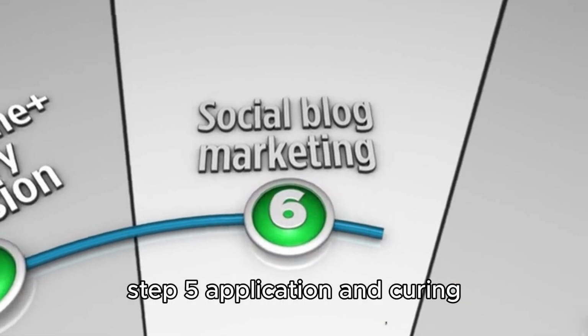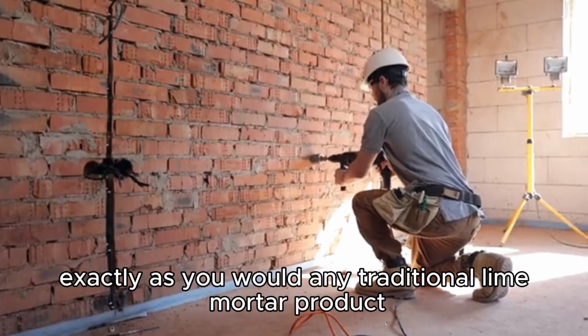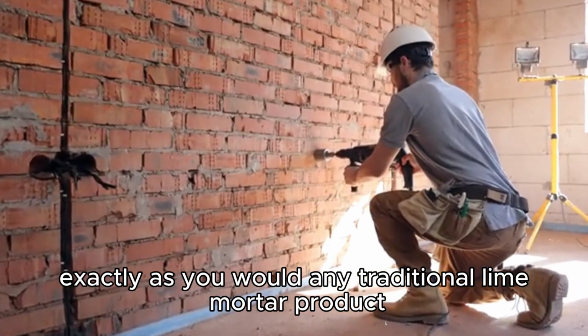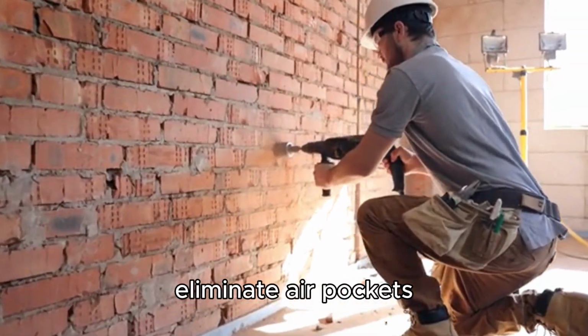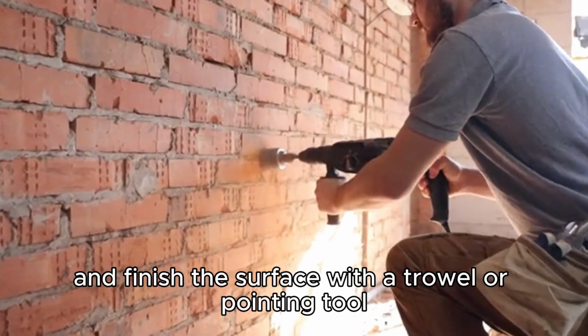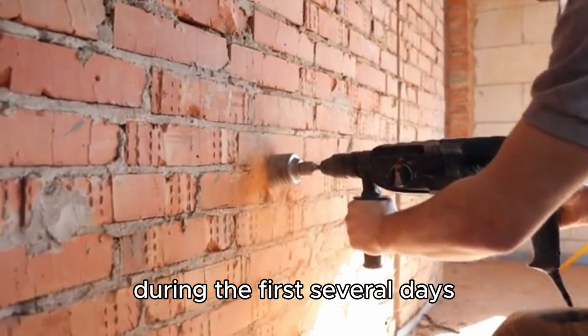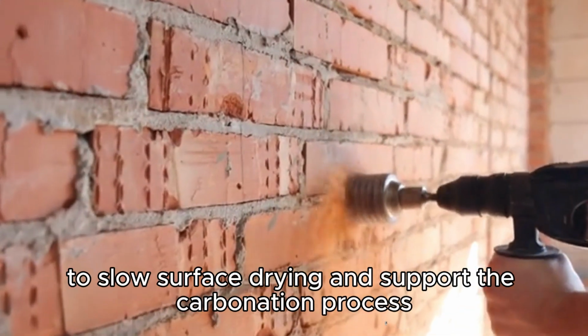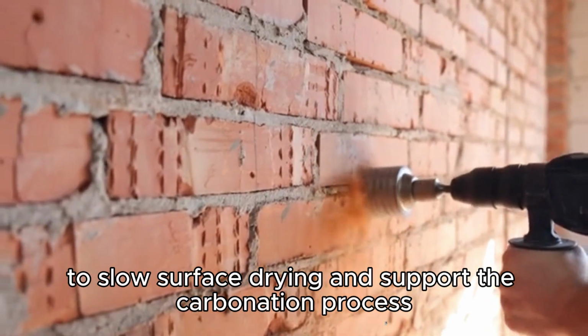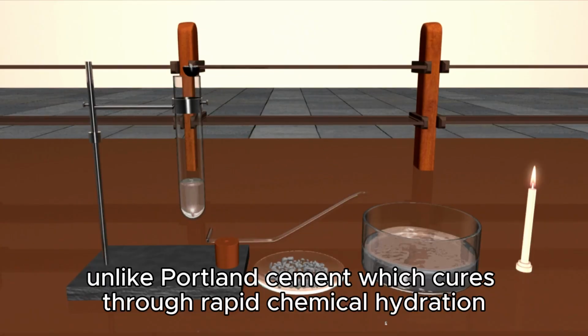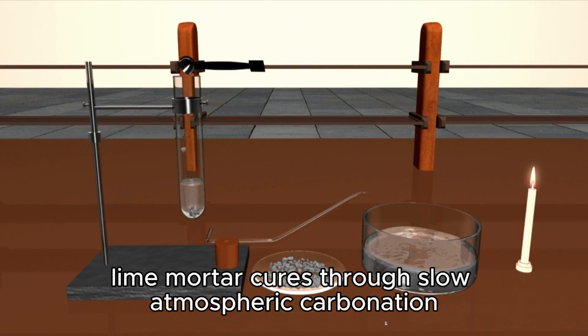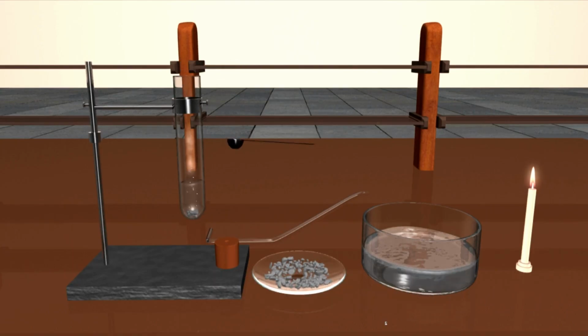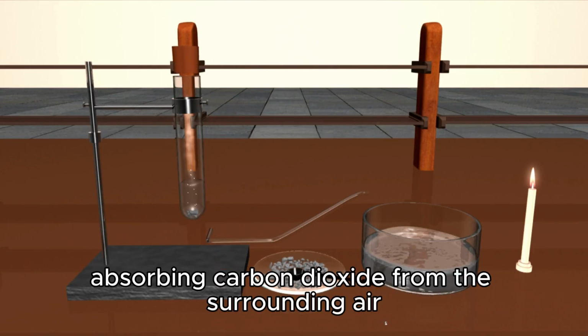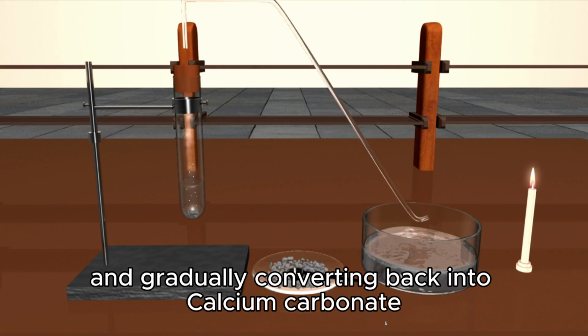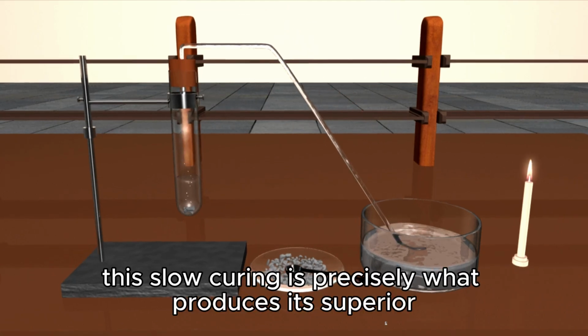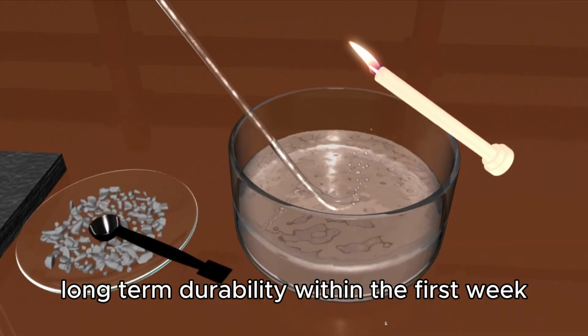Step 5. Application and curing. Apply the mortar exactly as you would any traditional lime mortar product. Pack it firmly into joints, eliminate air pockets, and finish the surface with a trowel or pointing tool. During the first several days, mist the finished work lightly with water to slow surface drying and support the carbonation process. Unlike Portland cement, which cures through rapid chemical hydration, lime mortar cures through slow atmospheric carbonation, absorbing carbon dioxide from the surrounding air and gradually converting back into calcium carbonate. This slow curing is precisely what produces its superior long-term durability.